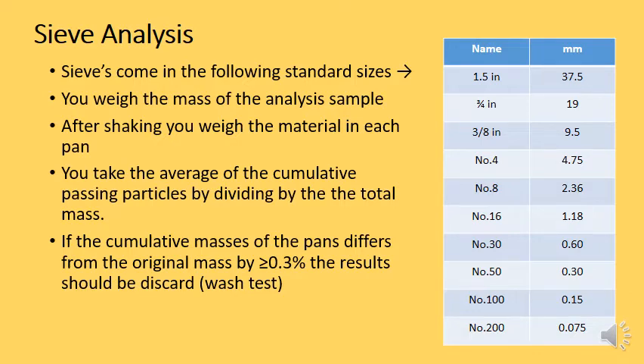Now, when you do the sieve analysis, you first take your sample and you weigh it. And then you place it in the sieves and you shake it, and then you weigh the amount in each sieve. Now that will be a percentage of the original weight. You take the total cumulative weight of particles passing through each sieve. So this is the entire weight of the aggregate that is smaller than that sieve, that fell through that sieve, and you divide it by the total mass, the original mass.